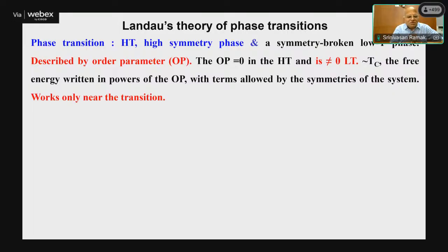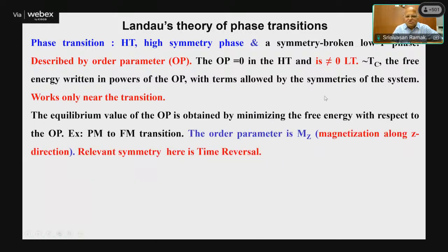So you must remember that Ginsburg-Landau theory is close to Tc. Far away from Tc, you have to tweak the theory a little bit. People have done that. But today I'm going to talk about Ginsburg-Landau, which works closer to the transition. So the equilibrium value of the order parameter is obtained by minimizing free energy with respect to the order parameter. The order parameter for a ferromagnetic transition is just magnetization. So the relevant symmetry here is time reversal.